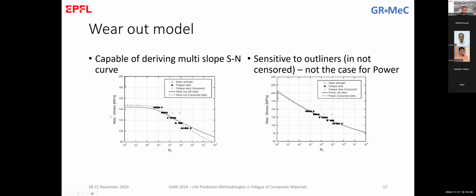So here, coming back to the previous discussion, here you have a good data set with closed symbols, and in this data set we have two outliers. And these outliers, although there are only two in a sample of more or less 30 specimens, they can cause problems. If you see here the fitting, the wear-out model with all the data, including these two open symbols, it is the black line, the solid black line.